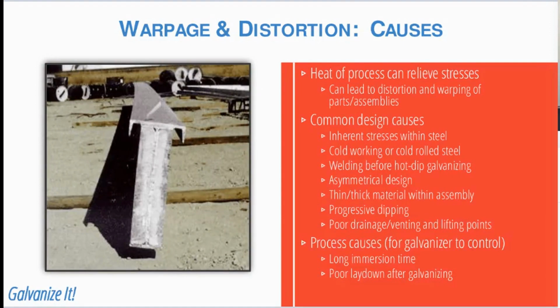The next design issue to discuss relates to warpage or distortion of some parts upon galvanizing. Some fabricated structures and assemblies might distort at the galvanizing temperature as a result of relieving stresses that are residual within the part from steel production and fabrication. Distortion is primarily reduced through design and fabrication measures that are intended to avoid or mitigate against high internal stresses. ASTM A384 is the specification which provides a list of design practices and fabrication techniques which make articles susceptible to distortion, including the inherent stresses within the steel, any cold working or excessive cold rolling of the steel. If there's welding, welded fabrications, especially ones that are asymmetrical in design, the combination of thick and thin materials in the same parts, these can also be products susceptible to warpage or distortion.